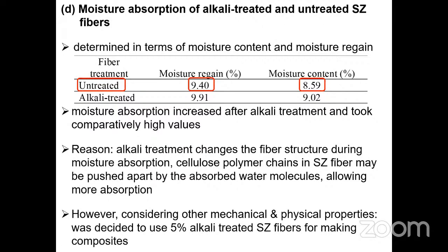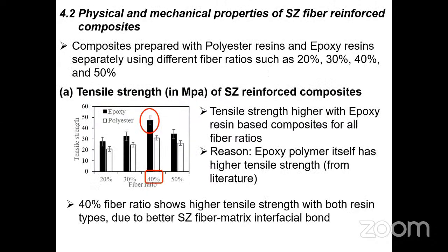However, considering the mechanical and physical properties, we decided on 5% alkali treated fibers for making composites. Now let's look into the physical and mechanical properties of Sansevieria zeylanica reinforced composites. Composites were prepared with polyester and epoxy resins separately, using different fiber ratios: 20%, 30%, 40% and 50%.